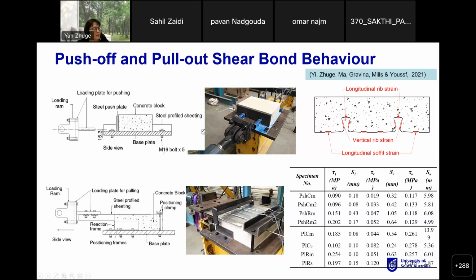Okay, so that shows where we put the strain gauges in the different locations, and these are all different types of mix designs we used. Then the results we found were about shear strength and also the maximum bond displacement. You can see that longitudinal shear bond really governs the load carrying capacity and performance of the profiled steel reinforced composite slabs. So that's very important, the shear bond behavior.